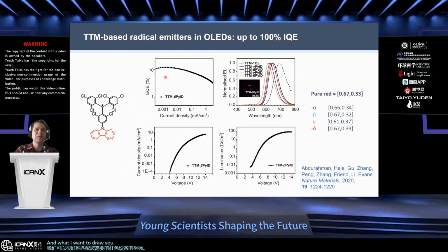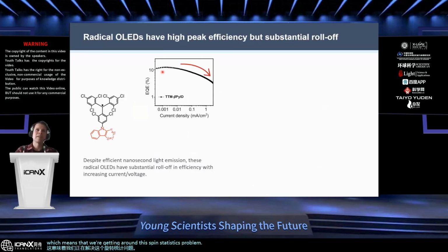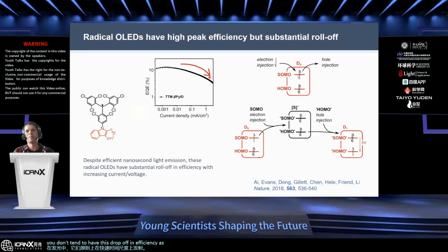And what I want to draw your attention to in these organic light-emitting diodes is that the efficiency that we can reach, at least at low current density, is above 10% external quantum efficiency, which means that we're getting around this spin statistics problem. But it's true that as you run these devices to higher voltage and higher current density, the efficiency drops off, which was something that we didn't really expect, given that, as I told you before, these materials were efficient in luminescence and they emit on fast timescales. In principle, you don't tend to have this drop off in efficiency as you go up.